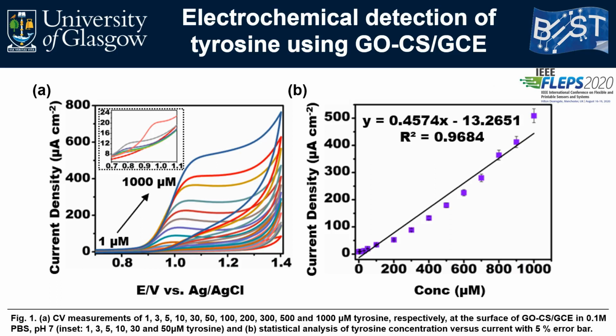The electrooxidation of 1 to 1000 micromolar of tyrosine dissolved in aqueous hydrochloric acid solutions was first assessed at the surface of the graphene oxide Chitosan glassy carbon electrode in 0.1 molar phosphate buffered saline solution at a pH of 7 using cyclic voltammetry. As seen in Figure 1a, upon the addition of 1 micromolar tyrosine, an oxidation peak with a current density of 8.6 microamps per centimeter squared emerged at 0.78 volts.